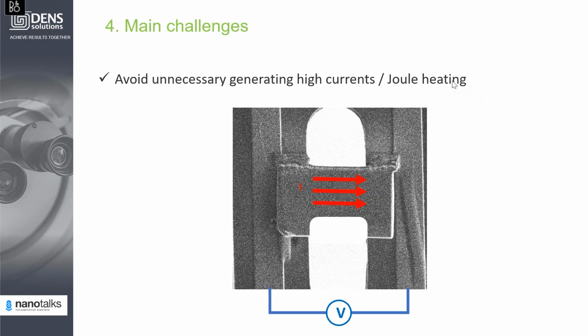The last part is that we need to avoid generating high currents or Joule heating. For example, if you're looking to study the effect of electric field on a sample, but the sample is prepared to measure current, so you have two welding points, it means that while ramping up the voltage or electric field, you will generate a lot of current in your sample. Instead of seeing the effect of electric field, you will see the effect of Joule heating on your sample.